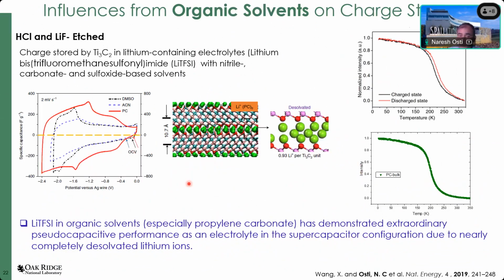Now, we tried a lot of different types of ionic liquid systems to look at the electrochemical performance, but at some point we decided to look at the electrochemical performance of the MXene, which is synthesized using a solution of hydrochloric acid and lithium fluoride. That's the mixture we use to etch the MXene, and we looked at the electrochemical performance of these MXene electrodes using lithium TFSI and three different organic solvents: dimethyl sulfoxide, DMSO, acetonitrile, and propylene carbonate. What we found is that once we have the propylene carbonate, it had a very enhanced, extraordinary pseudocapacitance performance, which is well represented by this red curve.